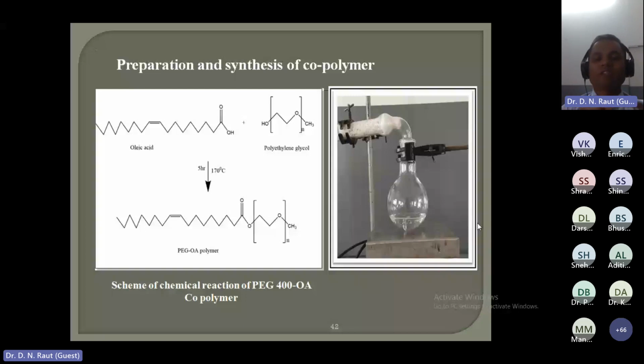There is a critical step: we have to choose the molar ratios of oleic acid or fatty acids as well as PEG of different grades, so that the chemicals could incorporate, and so that the hydrophilic and hydrophobic balance is right. That balance should be there so that it could form that self-assembly or nano-sized particle.